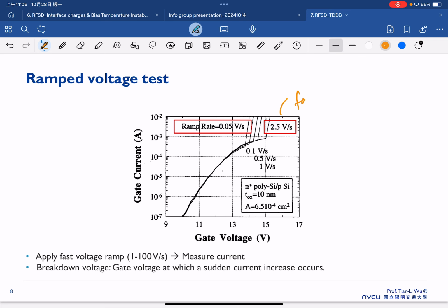So the fast case gives us a high breakdown, but the slow case gives us a lower breakdown. That already implies that when we characterize our device, you should be careful about how you set up your sweep, how you set up your step. Usually we can't change the speed of every machine,